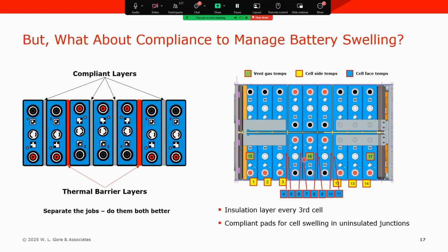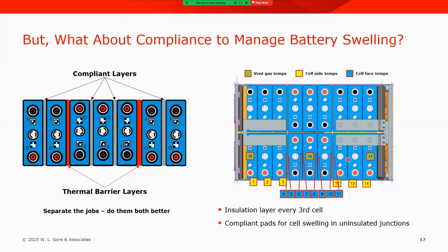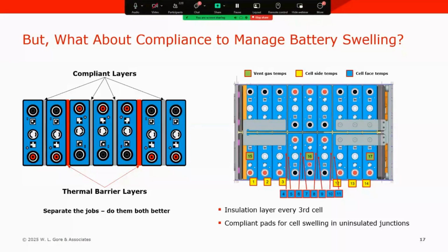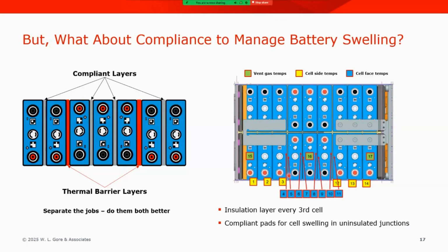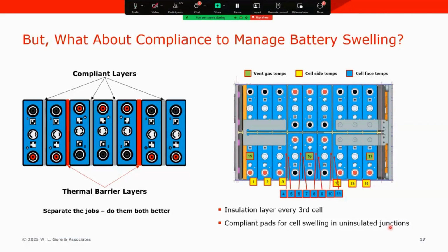In this experiment, we have 18 prismatic cells, 2 rows of 9, and the center cell, shown here by number 16, is going to be put into thermal runaway. We have protective materials, thermal barrier materials, in the gaps every third cell. So here between number 4 and 5, and again between number 10 and 11, we're going to have a thermal barrier material. And the alternate junctions, the uninsulated junctions, are fit with simple compliant pads.